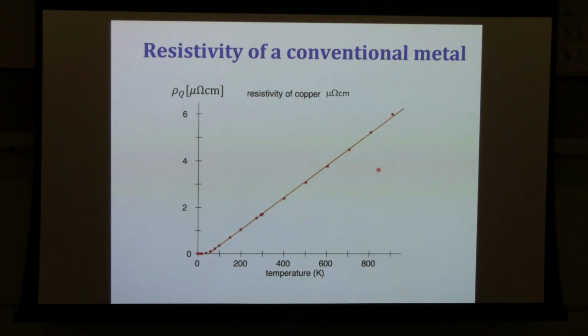Okay, so this is an example of what this theory can give. This is the electrical resistivity of copper as a function of temperature, and you see here different regimes, and all these different regimes can be described very well by basically Fermi liquid theory plus Boltzmann transport theory, fitting just a few parameters from experiments.